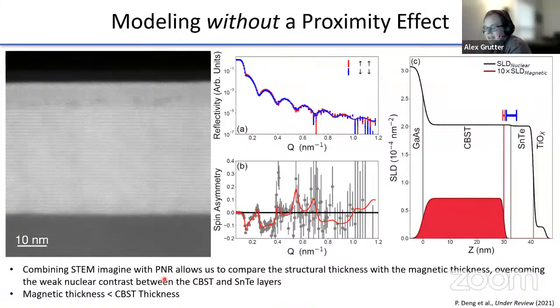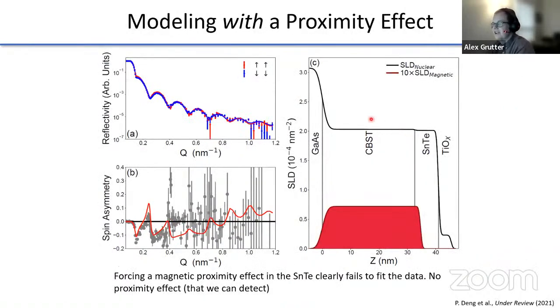Effectively the magnetic thickness is lower than the thickness of the chrome doped bismuth antimony telluride. And we can show you a counterexample here, where if you force the magnetization to extend into the tin telluride, your fit gets pretty horrible very quickly. You can see how all of a sudden the red line is not going through any of the points within error. So there's no proximity effect in this system that we can detect.